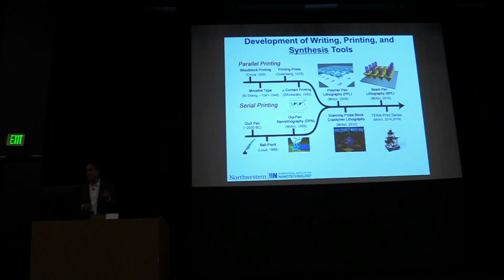That is really a big deal because most of the time when people show you something made by scanning probe lithography, it's been magnified up to 1,000 times. You can't physically even see it. Here you can make structures that you typically associate with high-end microelectronics and nanoelectronic type techniques. But in addition, what these tools do is they open up a new domain in synthesis. The ability to locally control chemistry, study reactions within these types of reactors in a very deep way, and to make materials faster than I think we've ever seen before. And I think that bodes well for using them to ultimately discover all sorts of new structures that have unusual properties that can impact many areas.